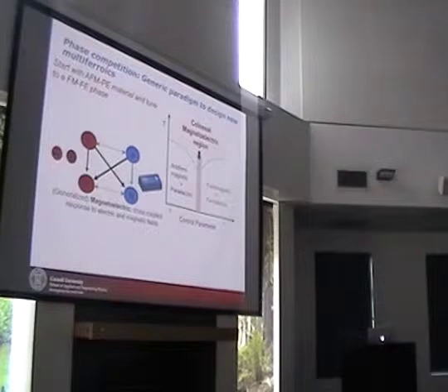Multiferroics: a material that has a spontaneous electrical polarization and a spontaneous magnetization. These are inherently multifunctional, in the sense that they respond in a useful way to more than one external perturbation, such as an electric field coupling naturally to a polarization, and a magnetic field coupling naturally to the magnetization. Again, this is a homogeneous single-phase material. But really the goal in this field is to increase functionality by taking advantage of a magnetoelectric effect. That is what I'm calling any cross-coupling between these two very different order parameters.